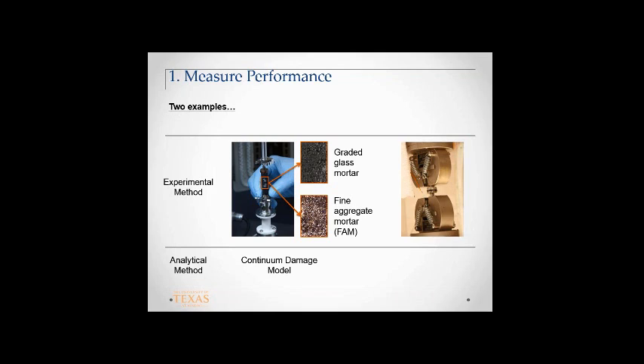There's another paper, well, it's not a paper yet because it's still a draft. But looking at these diffusion times, and how much time it takes for the material to diffuse and mix with recycled material in the absence of rejuvenator, is something we've tried and something that you should do. Those are important questions. In fact, what happens if you mix the rejuvenator with the RAP stockpile and leave it there for a day or two and then mix it with the binder? You allow it to marinate.